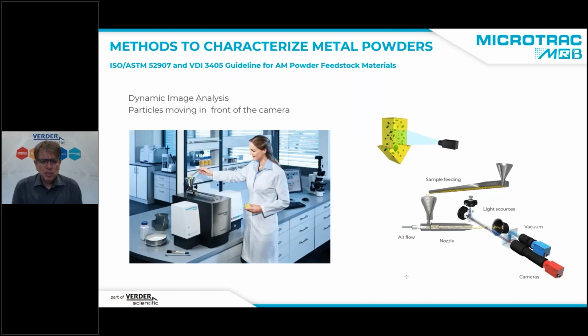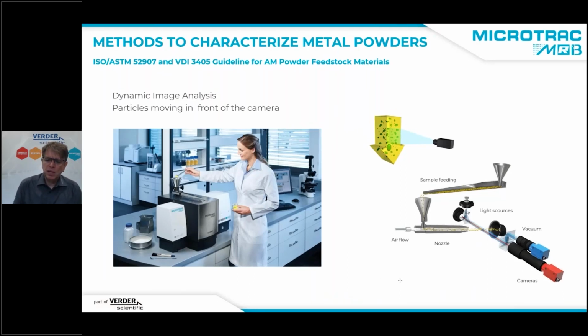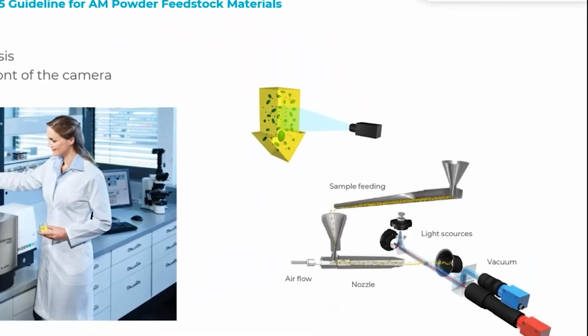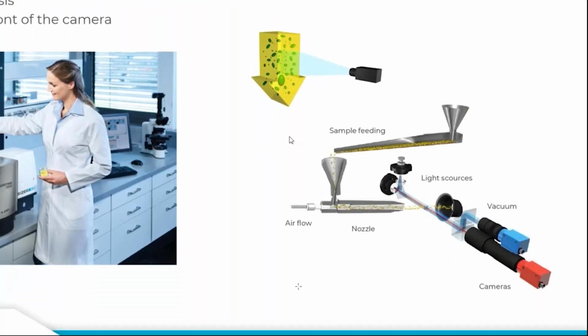So how does the dynamic image analysis work? Basically, we have a camera and we let the particles move in front of the camera. This is the basis for the name dynamic image analysis. We have a camera at a fixed position and we are moving the particles in front of the camera. In reality, you take a teaspoon or 2 teaspoons, maybe 5 to 15 grams of metal powder, and put it in a funnel. Then we have a hopper. The material is moving on this hopper, falling into a small funnel. And with the air pressure, the particles are dispersed. That means we have single particles, not many particles at the same time. Then these single particles are flying through our detection area, where we measure the particle size with 2 cameras, and then the particles are collected in a vacuum cleaner.